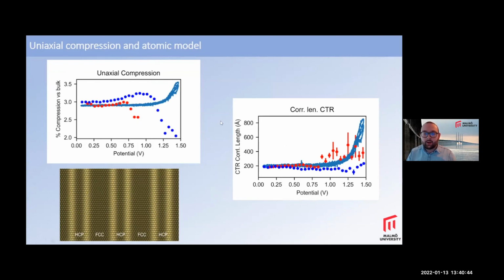So in this case, we've converted the stripe separation, which is based on the position of the reconstruction peak, into a uniaxial compression of the surface layer versus the sort of normal bulk layer. And what you can see is as you go higher into potential, the surface becomes a little bit more compressed before it lifts, and then it lifts. And this matches fairly well with the signal from the CV. And then you could also look at, for instance, the correlation length of the 111 surface.